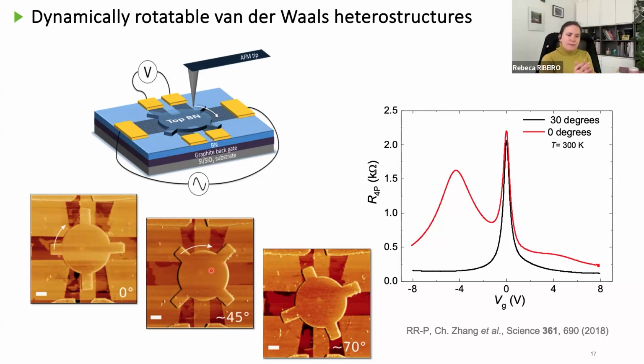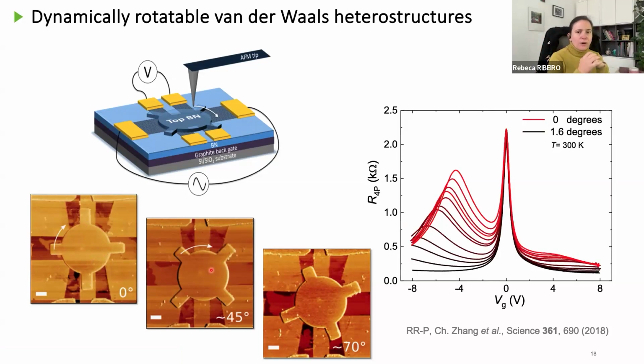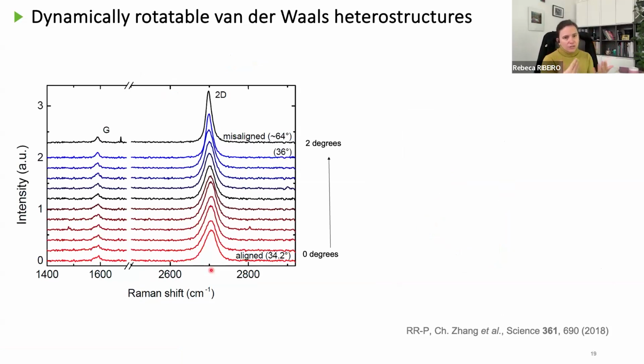Now, the extra step that we did for this was we installed electron transport measurement inside of our AFM, which in fact allows us to measure every single angular alignment for these cases between 0 and 1.6 degrees. So we can now measure transport and we can stop at any angle that we want. And okay, this is beautiful, but what else can we do with it? Since our devices are built in a way that they do not depend on the AFM, which is used to change the angle, they don't need to be inside the AFM. We can also measure optical properties.